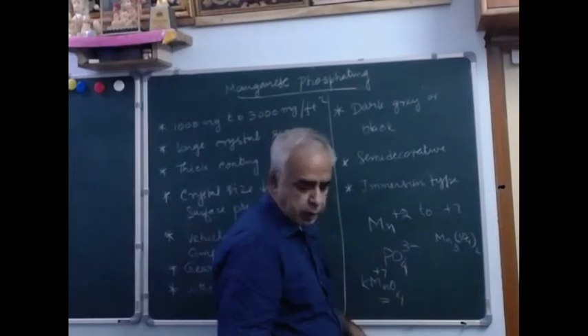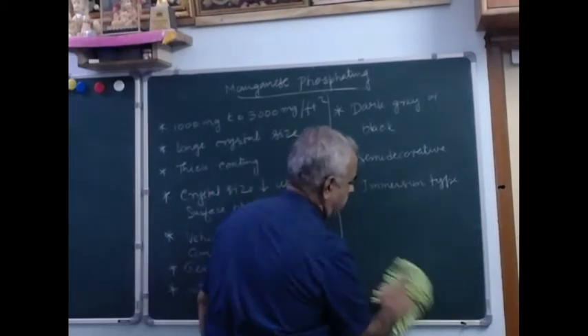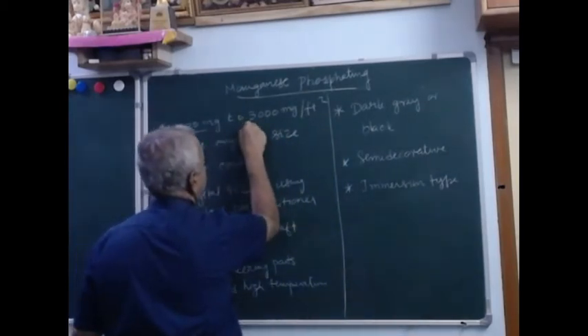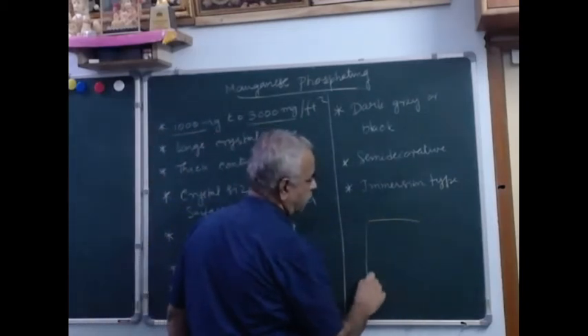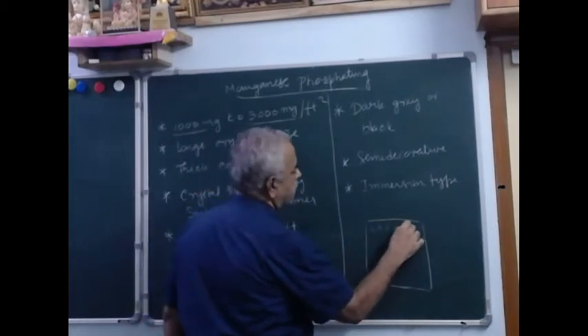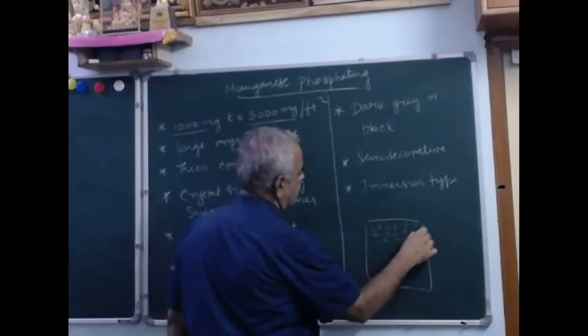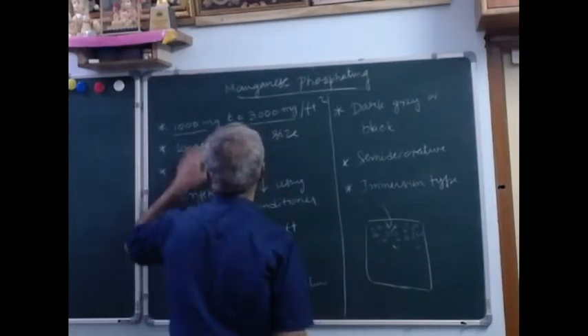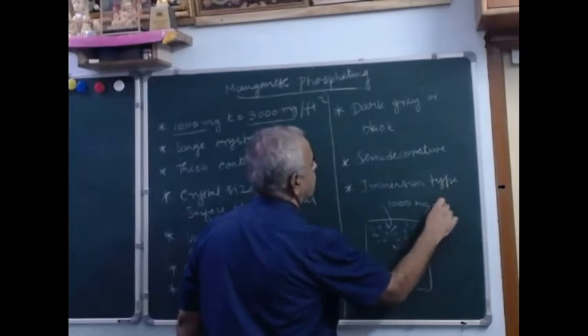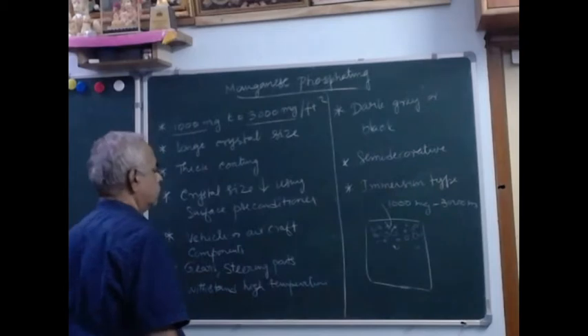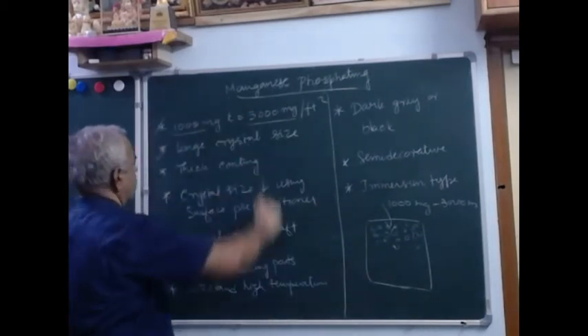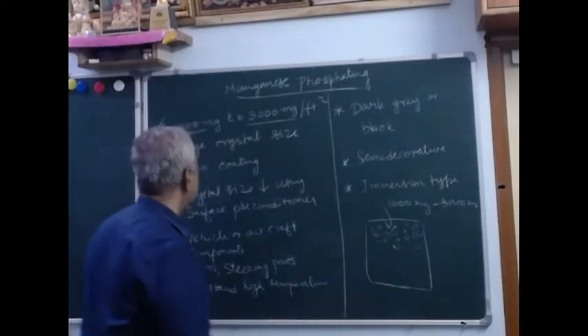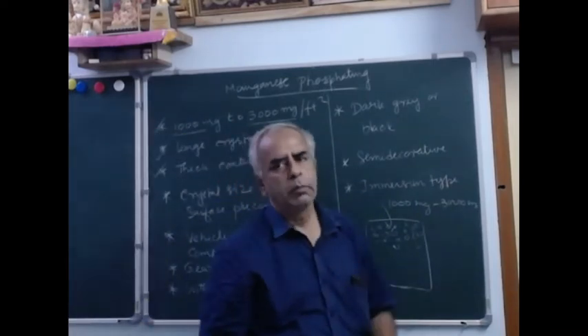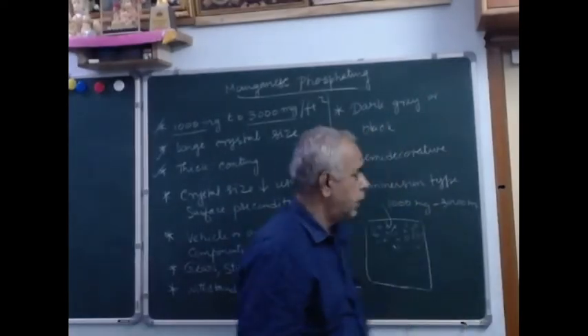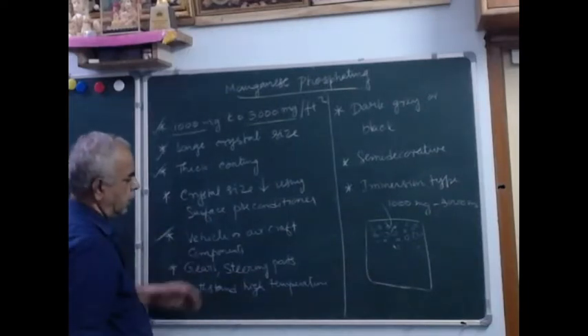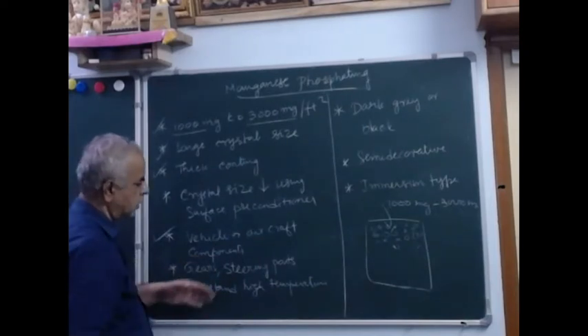Okay, right. But the major content is manganese, and it's a heavy phosphate. Its coating weight is 1,000 milligram to 3,000 milligram per square foot. Suppose you consider a component of 1 square foot surface, it will form a porous surface, and it will be coarser also. The crystal structures will be coarser, and they are larger crystals. As I already suggested, they form a very thick coating. So this is not suitable for painting, you must understand that. But it may be useful for greasing and oiling, and it is mainly applied on aircraft, helicopter components, heavy automatic gears, steering parts, etc.